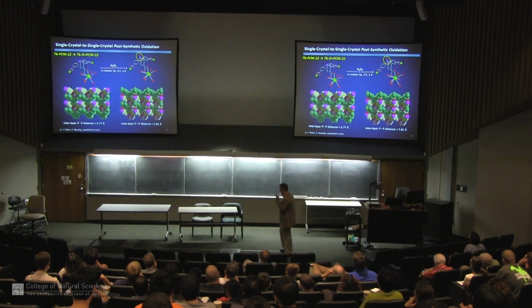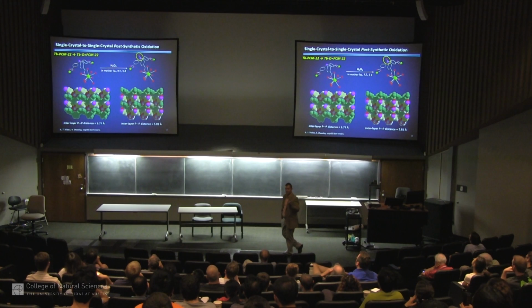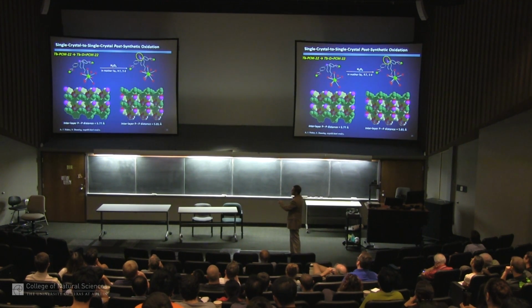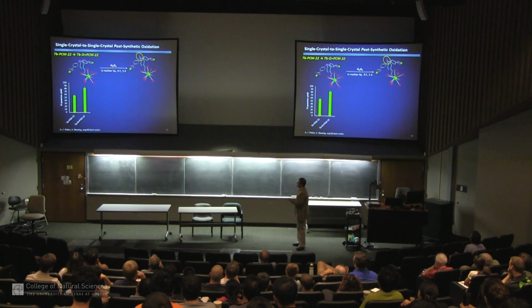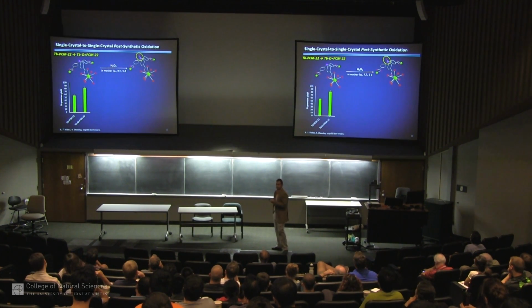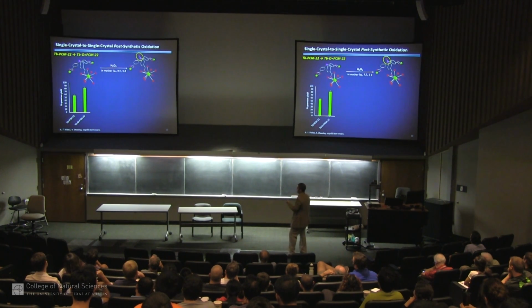And this is, again, because we have phosphines, we can do chemistry that other people would not be able to do. We can take the solid crystals, expose them to concentrated peroxide, and it doesn't digest the crystals, it just simply targets the phosphines and oxidizes them. And this happens in a single crystal fashion. So we dip our crystal in peroxide, put it back on the diffractometer, and now we can see all the phosphine oxides. It's done nothing to the structure of the material, but it's done something electronically important. What it does is increases the quantum yield to nearly 90%, which is about as good as you can get with these types of materials. And you can see all we've done is added this oxide.